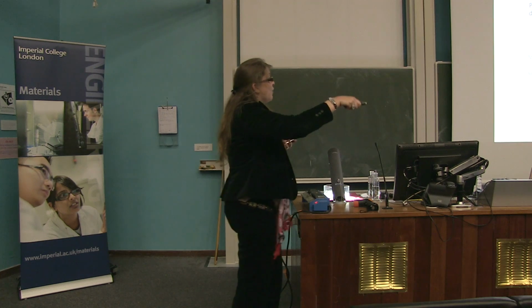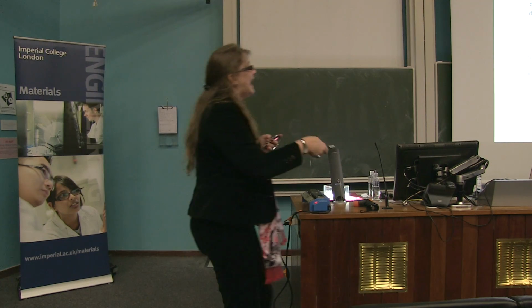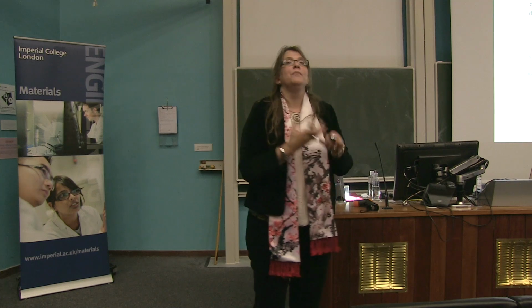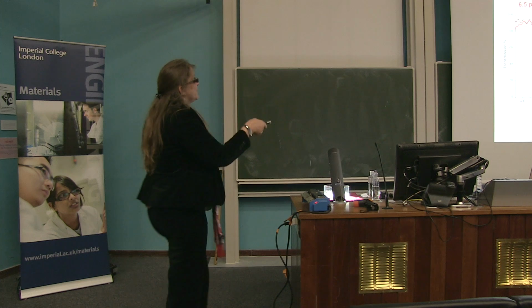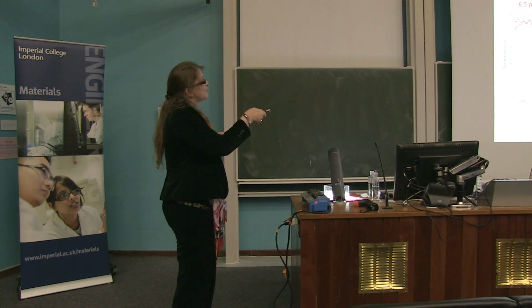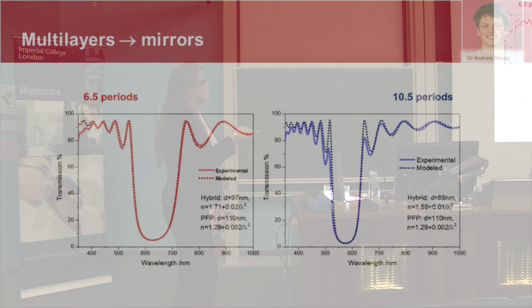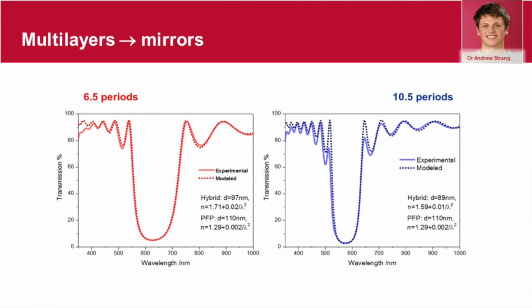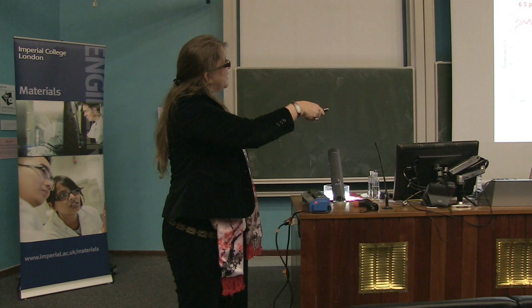And nature uses this all the time. So the Ulysses butterfly, beetles, they use these optical effects. And they get color not because they have a dye in there, but because of the clever usage of refractive indices. And now when we start to stack them, we can really precisely measure how much or what color is reflected. So we can measure transmission. So we take a slide like this blue slide we showed before, you shoot light in, and you measure essentially how much light gets through. So there's always some scattering, so you never have 100%.